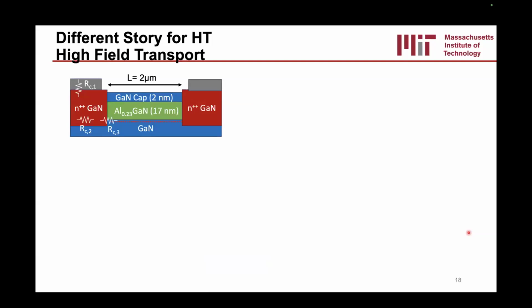However, interestingly enough, it's quite a different story in the high field transport case. Typically, the mobility is a low field transport parameter. And so we can actually try to understand what's going on in the high field. Since we have these TLM structures, or these resistor structures, we can break down the resistance components. It's basically 3 resistors in series: 2 in the contacts, and then the resistance in the channel.